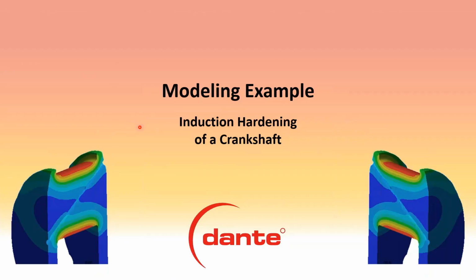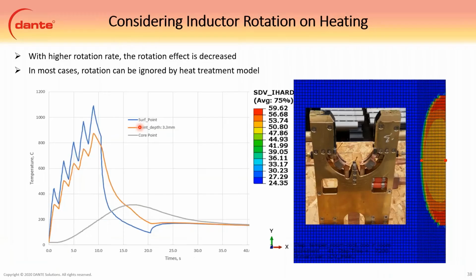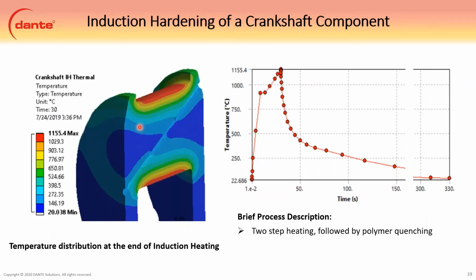So this is single shot induction of a crankshaft. Most of these single shots are still rotated, but generally the rotation rate is such that the temperature should remain uniform in the circumferential direction, so generally we ignore the rotation. However, if you really feel your rotation is messing up the process, it can be modeled. On the left is a temperature distribution at the end of heating, right before the spray quench starts. And this shows the 2-step heating process that was involved.